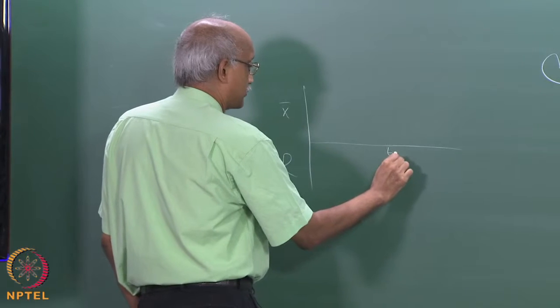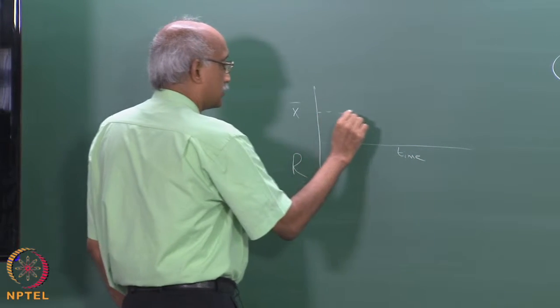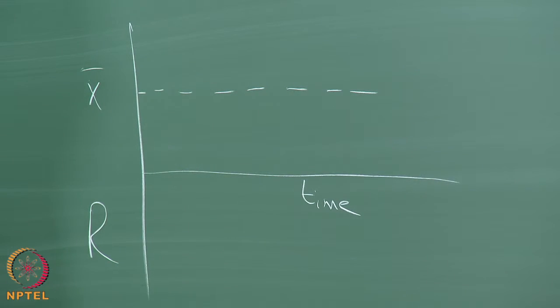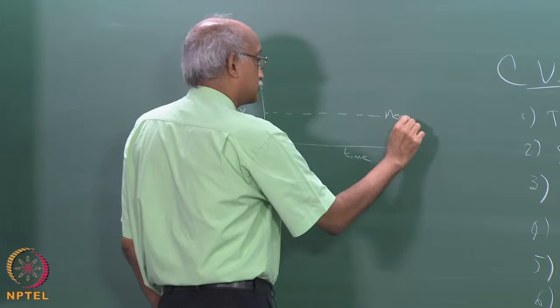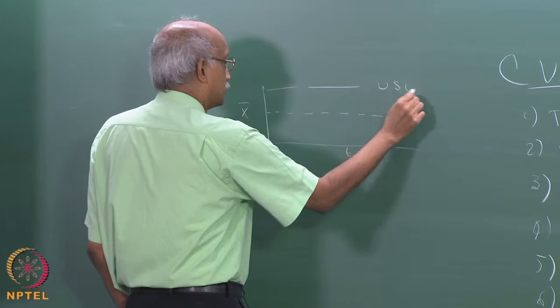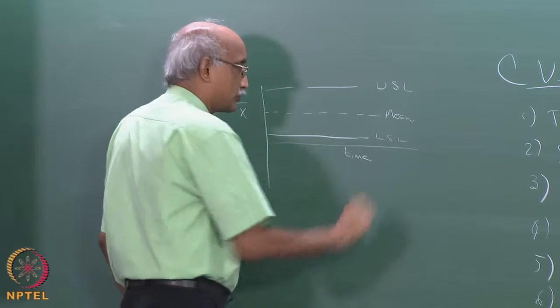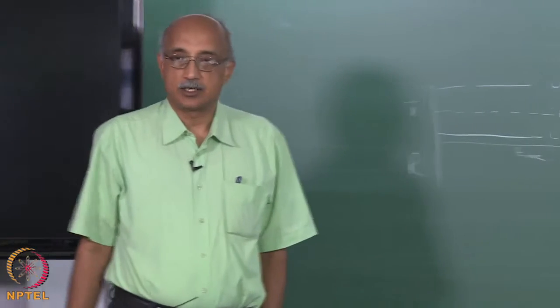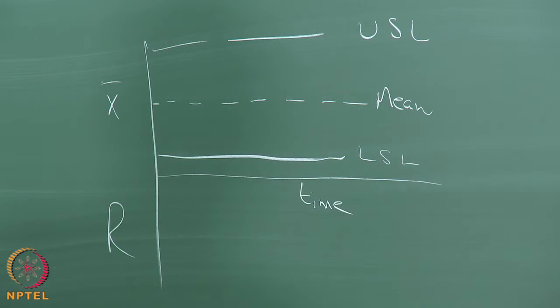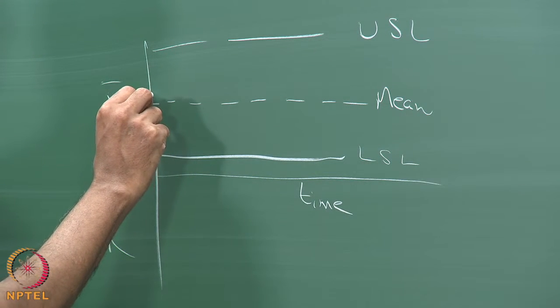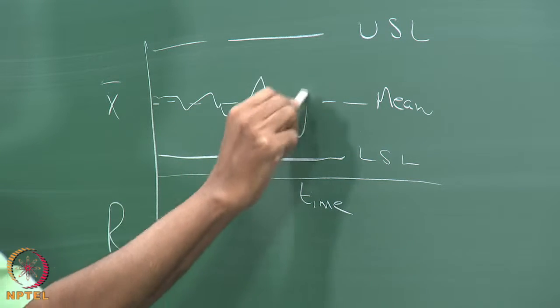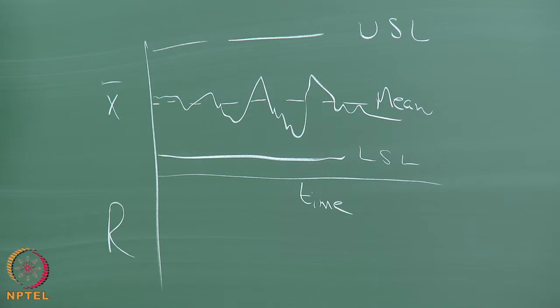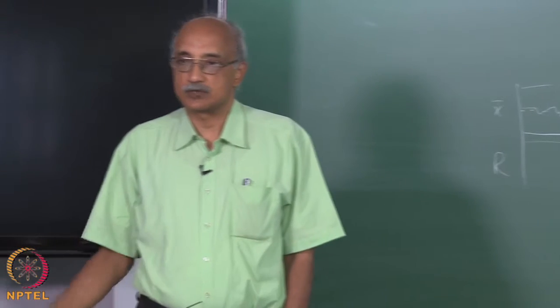So, you would measure this as a function of time, and there will be a mean for the process. There will be an upper spec limit, there will be a lower spec limit. So, for example, these could be thicknesses of the CVD film, and you would want to have a specification on it that is, let us say, plus or minus 5%. So, you would have these spec limits, and your mean would essentially show some trend like this. The first thing you would ensure is it stays within specs, because if it exceeds the spec limit on either side, you have to throw the product away.